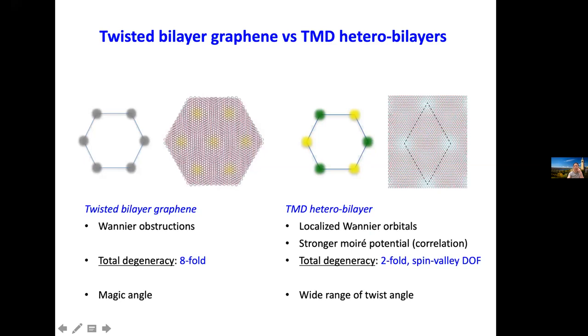The moiré potential is stronger, so that gives you more confinement of charges, and this gives you a strong correlation. And instead of requiring 8 particles to fill this band, we only need 2 particles to fill the first moiré miniband because we only have spin-valley coupled degree of freedom. And then, of course, we don't require a magic angle.